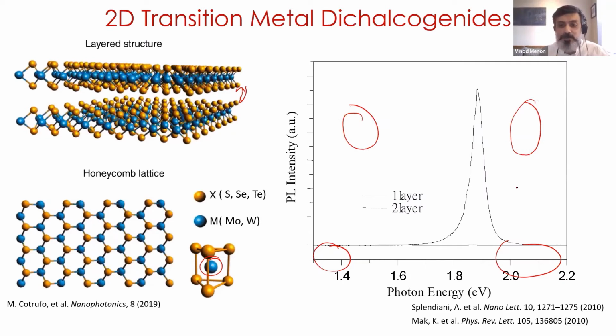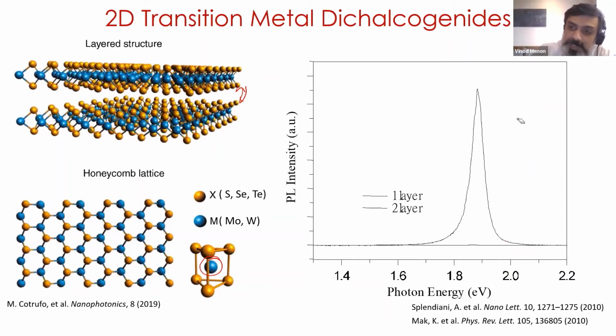And in fact, if you look at the photoluminescence from this material, you will see that the difference between one layer and two layer is 10 to the 3 compared to this number, about 1,000 times greater than this number. And so this clearly shows that you can get a huge amount of photoluminescence from this material just by going to this monolayer limit, because you're going from indirect band gap to direct band gap.